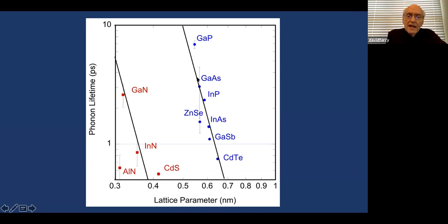Well, it turns out, remember this, the decay of the optical phonons goes with this 3-phonon process. And if you look carefully in your solid state physics books, sometimes you have to go back to the early editions of Kittel to find this. But there's the statement that the 3rd order elastic constants depend upon the bulk modulus to the -5th power. And the bulk modulus is directly proportional to the lattice parameter. So since the scattering rate is the square of the matrix element, that makes the bulk modulus to the -10th power. And so you get this curve, and that's fit to that.